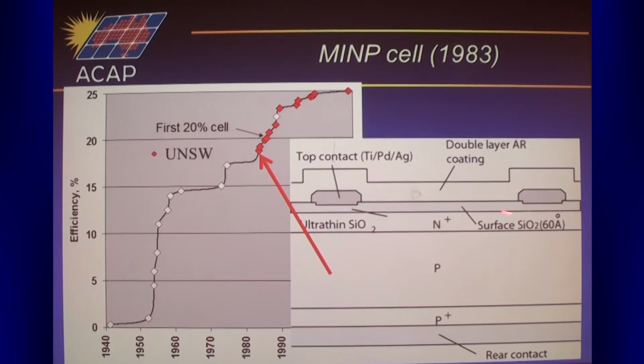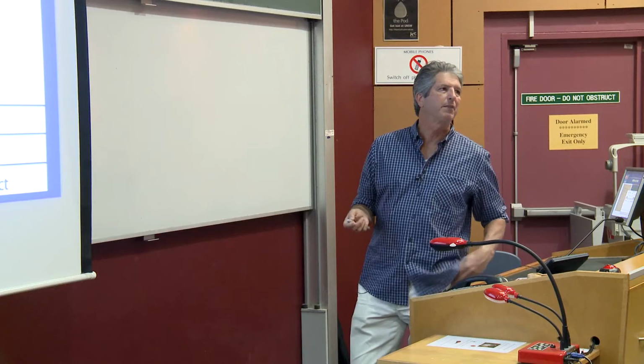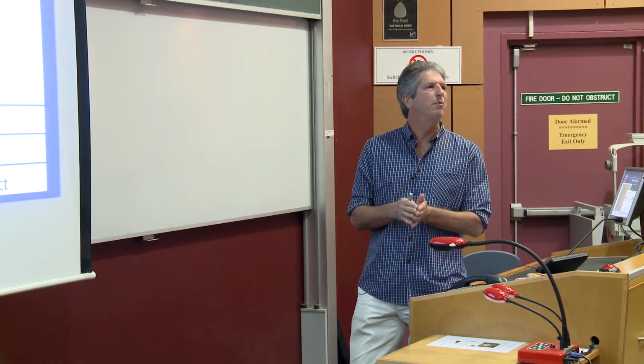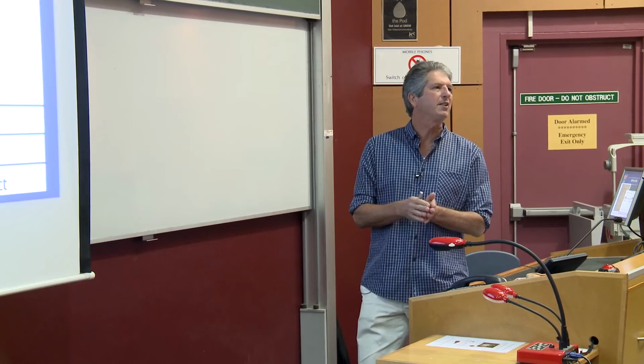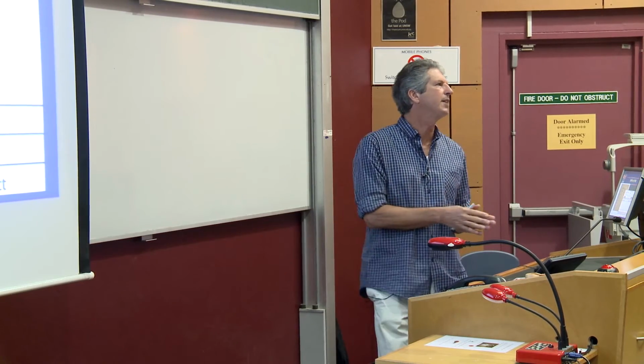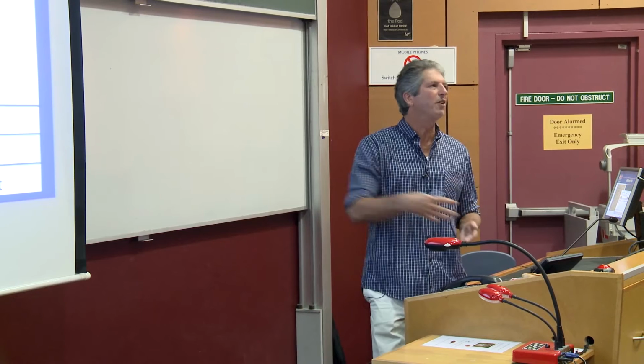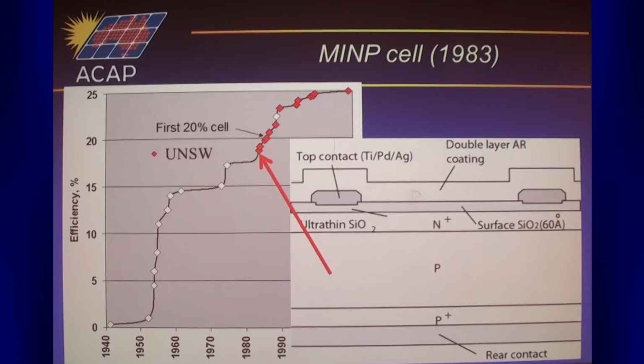So we initially put oxide along the surface, even under the metal contacts. So metal to silicon forms an infinite recombination velocity contact. So that's really bad news. Wherever you have a metal contact to silicon, S equals infinity, and you get all those linear gradients and extra current flow, etc. By putting this oxide under there, we could make that region look less damaging to the minority carriers. So this was the structure that gave us our first world record in 1983. So mainly it was an S reduction both along this surface and here.